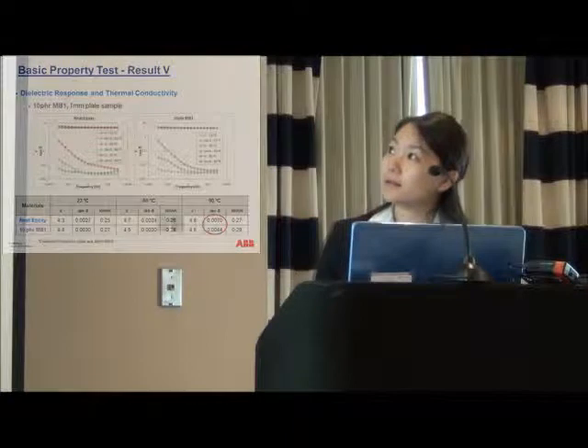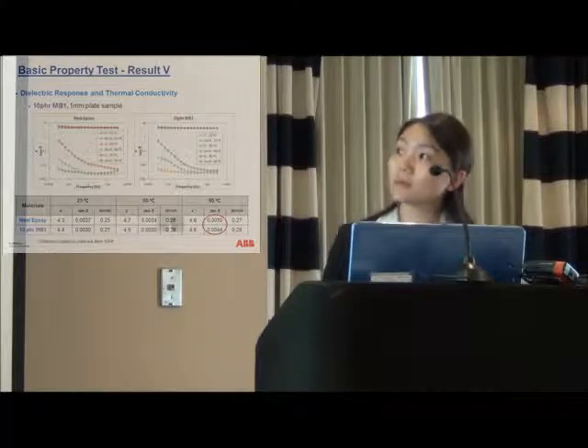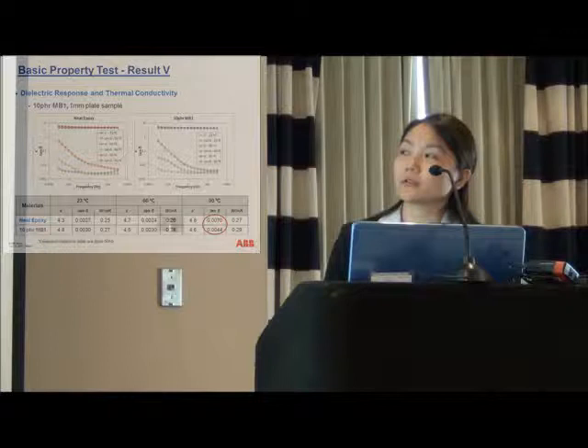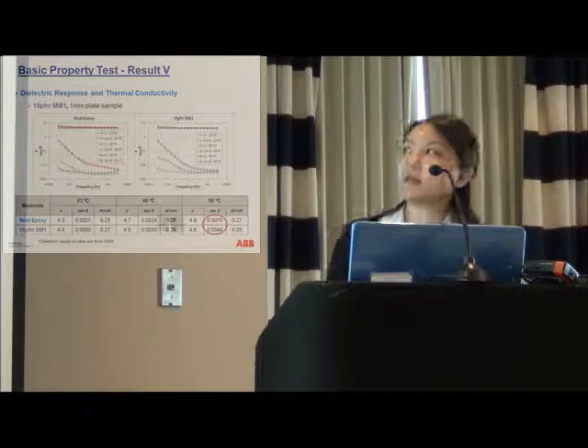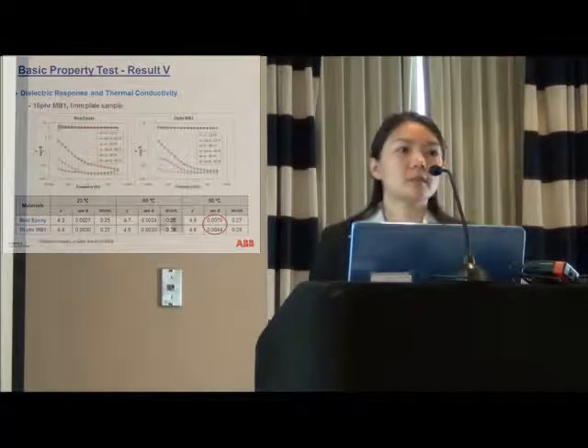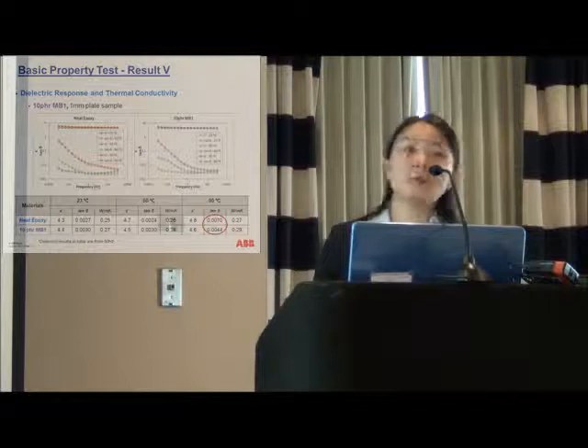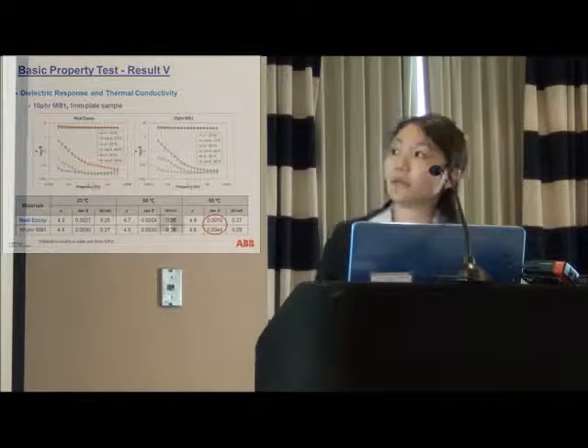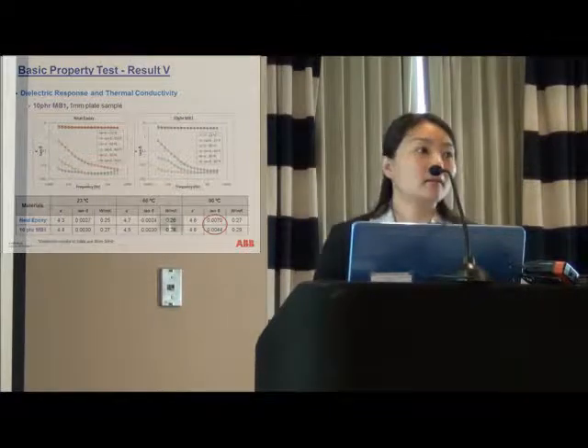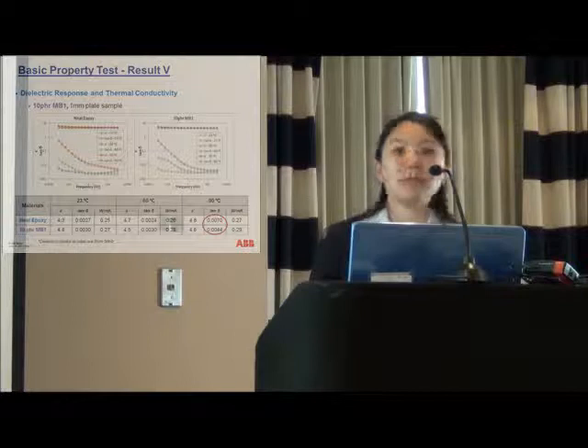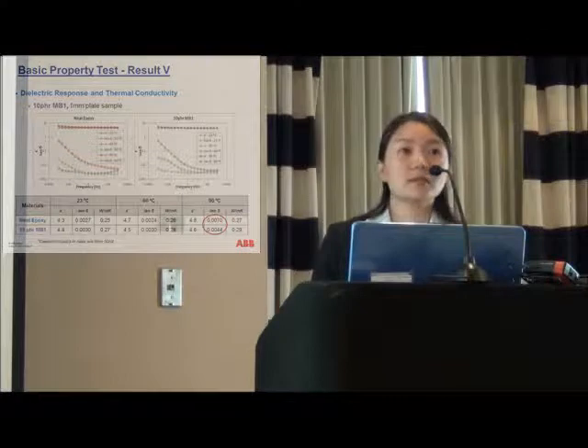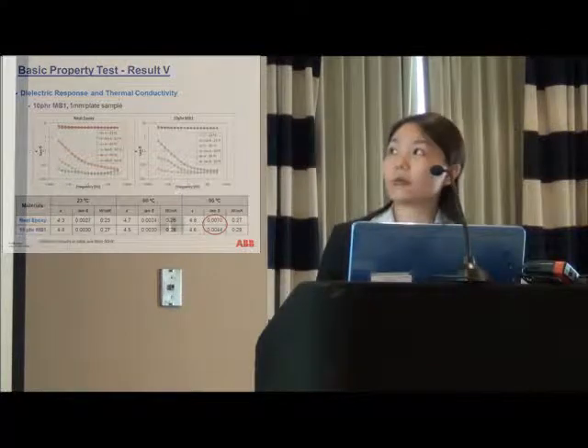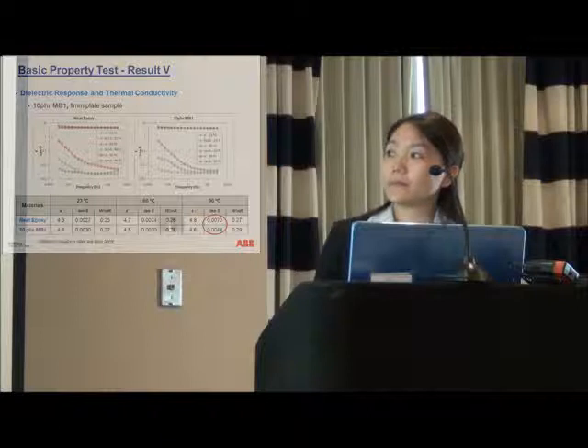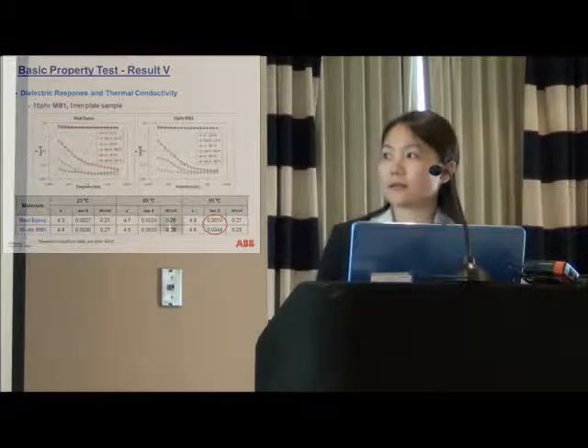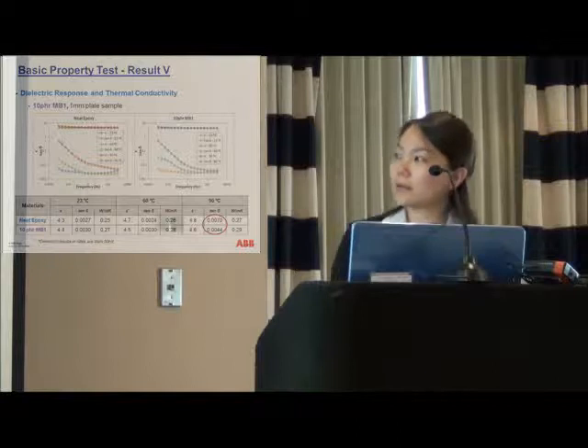And then the dielectric response - these are a lot of curves, so you don't need to read all of them. We tested the material, the nanocomposite and the neat polymer, at three different temperatures, and if you just look at the curve from far away, they look more or less the same. So we say there was no significant difference between the nanocomposite and the neat polymer for both the dielectric constant and the losses.